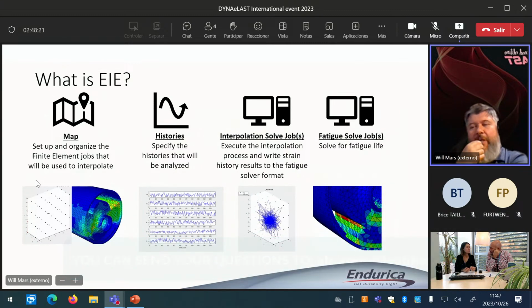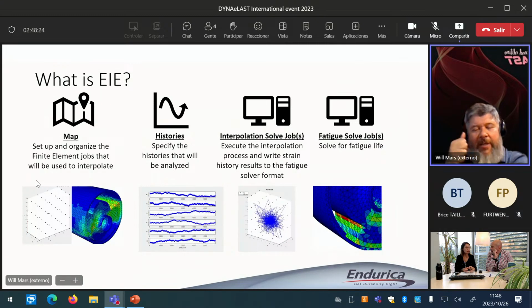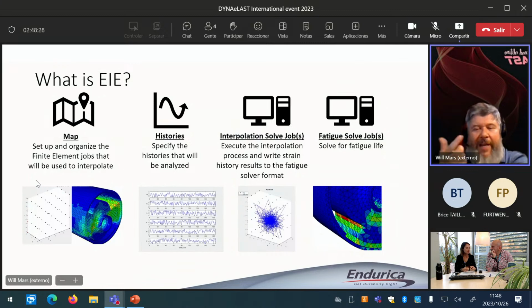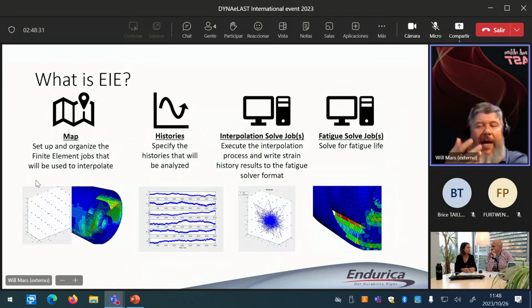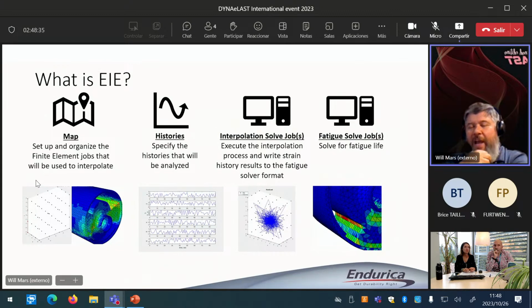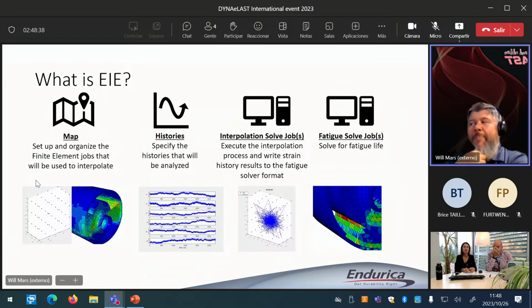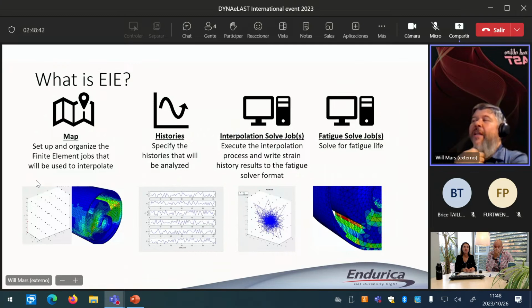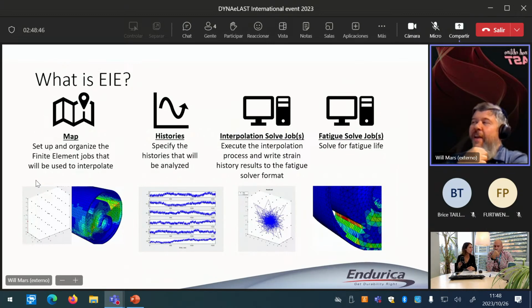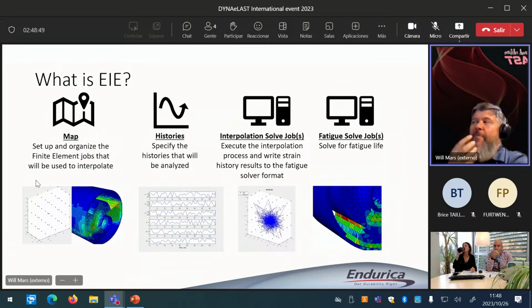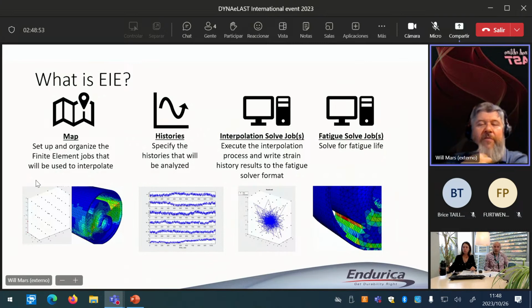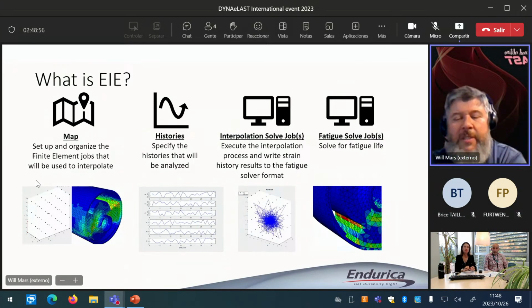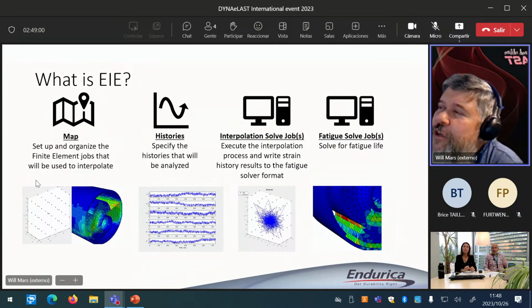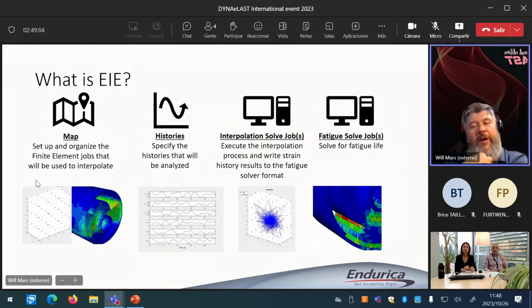What's really nice about this procedure is that it does allow us to account for nonlinear behavior. That's important because rubber is nonlinear in many ways. There's nonlinear material behavior. There is finite straining and kinematics. There is contact, and all of those different nonlinear effects can be represented using this mapped approach. And then finally, once we interpolate to get stress strain history, the final step is to solve for fatigue life. To do that, we would use either the CL or the DT solver, depending on the requirements for the analysis. In this case, we're going to use Endurica DT because we have a schedule of 144 events.